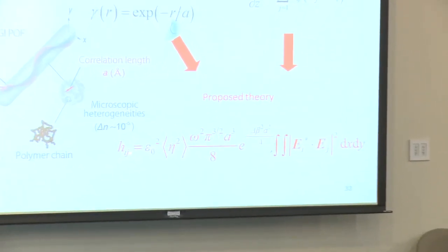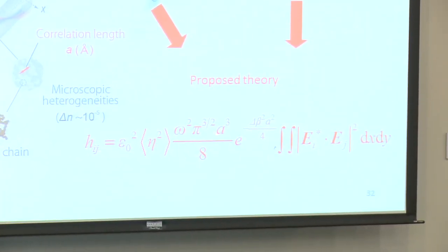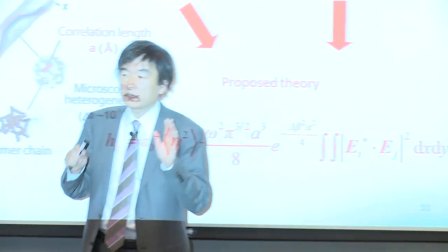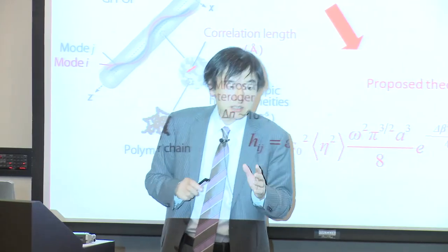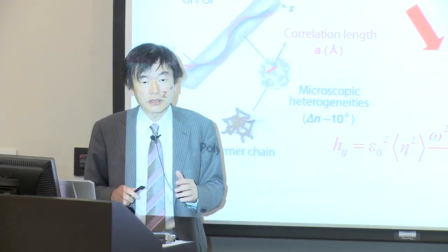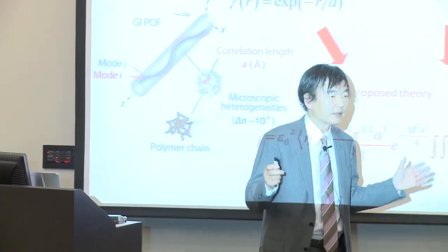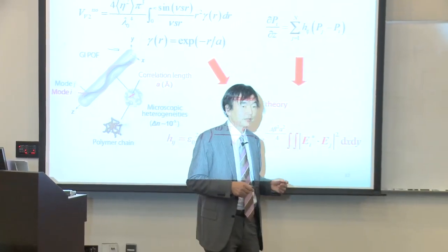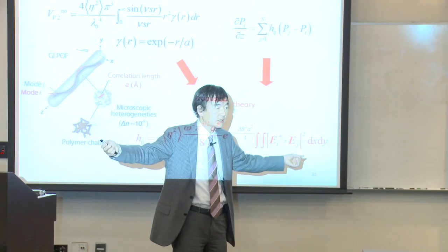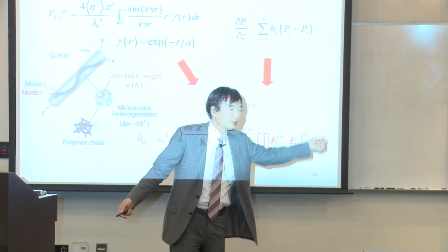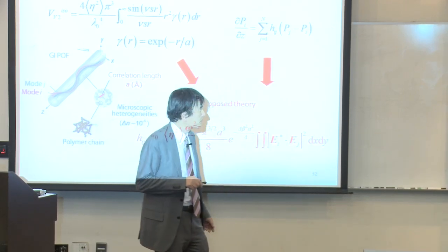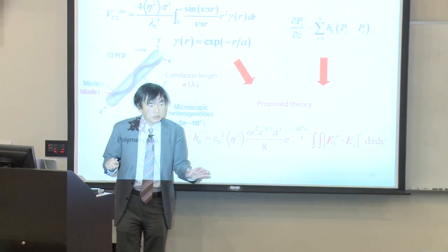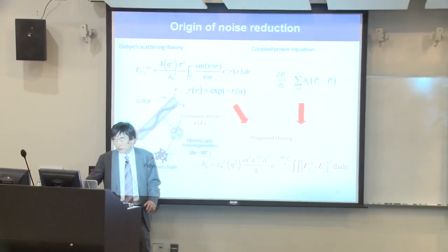Now, Hij is a coupling coefficient between the i mode and the j mode. Now, this is a function of the size of heterogeneities and the fluctuation of the different indices. So this is one dominant reason to dramatically decrease the noise. Sometimes the scattering loss is bad, so we minimize the size, but sometimes inside the house, we don't need the long distance. So such a fiber, a disposable one, is now very useful because the tiny heterogeneous structure almost completely eliminates the other ones.